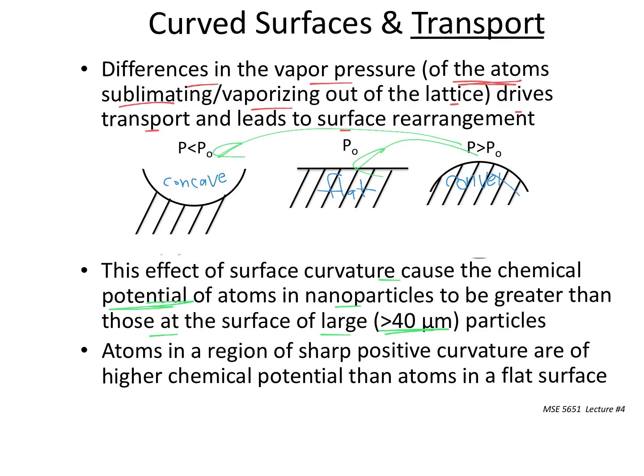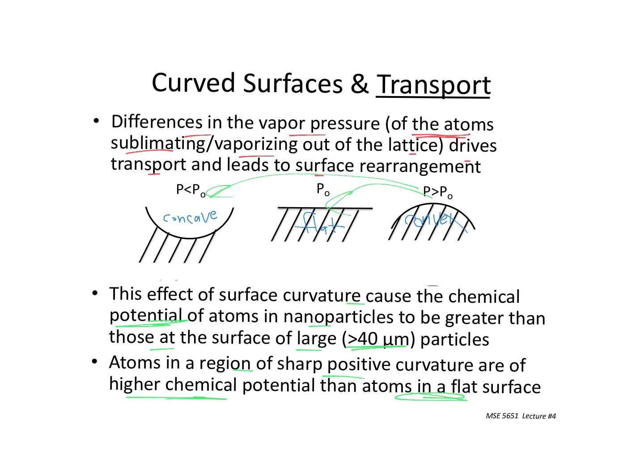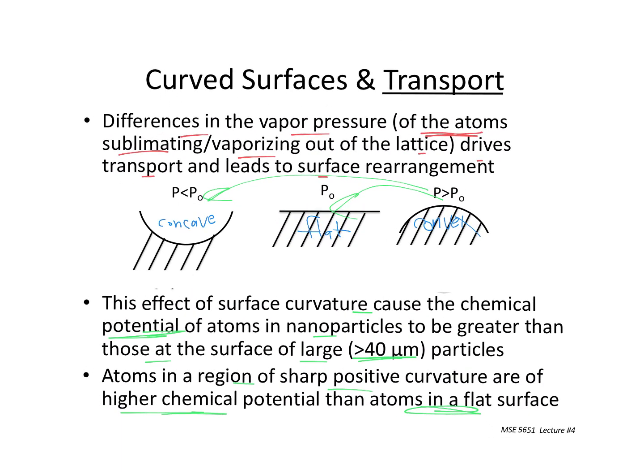So that also means that nanoparticles, which is where we're going with biomaterials processing, because we make the flaw sizes smaller that way, become significant here in terms of governing their properties, especially at higher temperatures. Atoms in a region of sharp positive curvature are of higher chemical potential than atoms in the corresponding flat surface. They want to leave and go someplace else. They don't want to be in these high energy situations where they have higher chemical potentials.